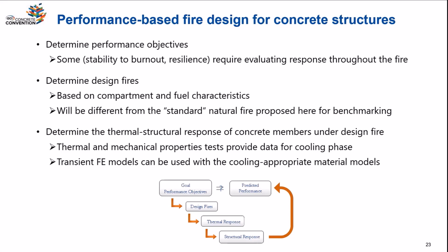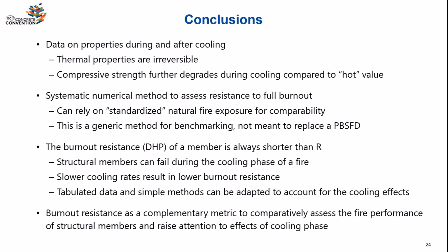But what's interesting as well is that we show the procedure to quantify the response of concrete structural members during the different phases of the fire, and notably to quantify burnout resistance, and that can be adopted with any design fire. So in conclusion, we have shown new properties during cooling. Thermal properties should be considered irreversible, and compressive strength further degrades during cooling compared to the hot value. We have shown a systematic procedure to assess the resistance to full burnout of different concrete members.